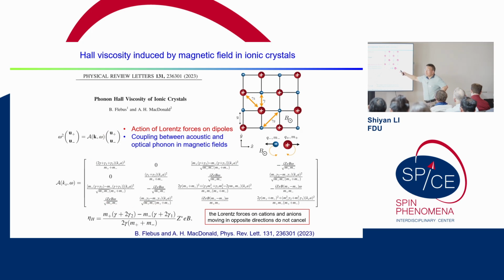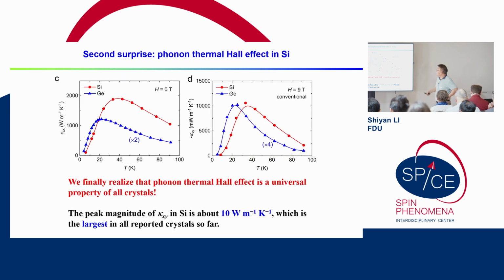Then in this theoretical paper, they said that for ionic crystals, yes, there should be a thermal Hall effect. But I think they didn't do the calculation, and they cannot get the right number to compare with the experiment. Okay, then if an ionic crystal can have this thermal Hall effect, what if we measure a single crystal with only one element, a pure element? So we immediately thought about silicon, right? It's an intrinsic insulator, very insulating at low temperature. So we measured it, and this is the thermal conductivity, and the thermal Hall is very giant, even the largest one.